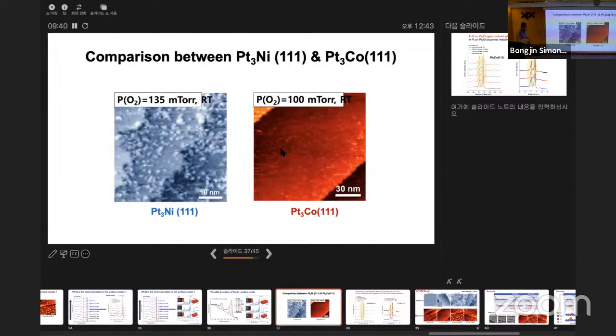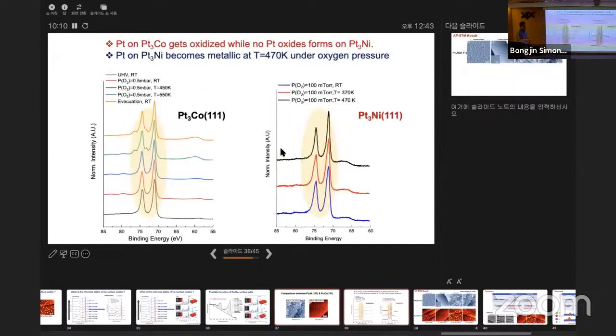So it comes down to these two: a comparison of platinum-3 nickel and platinum-3 cobalt. Clearly, at around 100 millitorr of similar pressure, 100 millitorr of oxygen at room temperature, it is clearly different. And platinum cobalt seems more stable at this temperature and this pressure. But when you increase the temperature a little further, then it's completely different.